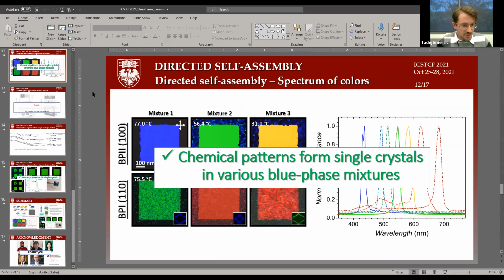Yeah, well, not really, but there is one thing, right? Because blue phase 1 and blue phase 2 have a crystalline structure. Blue phase 3 is like an amorphous state. So I don't really know what to expect in this case, if it's possible or not. Well, there are some studies that maybe it's possible to have a crystal, but it is not completely stable. So the thermal fluctuations, well, you know, in blue phase 1 and blue phase 2, the range in which you can find the phase is very, very narrow, no? Something like 0.1, 0.2